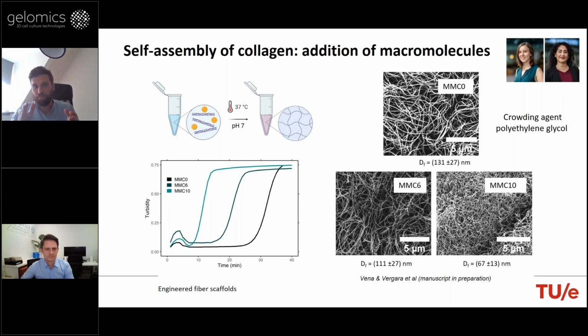So it's really just occupying space and confining the material, which we believe leads to this faster fibrillogenesis time. Basically, if you have a PEG-based solution and you're adding collagen, your expectation would be that the collagen is not homogeneously distributed throughout, but there would be, on the nanometer scale, pockets of collagen where they can. Okay. Exactly. Yeah. I think that makes a lot of sense.